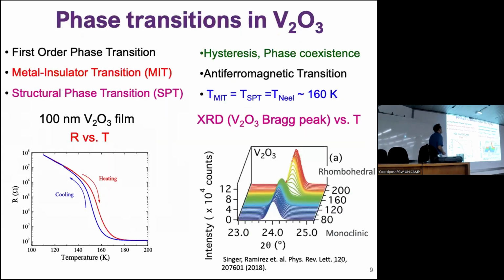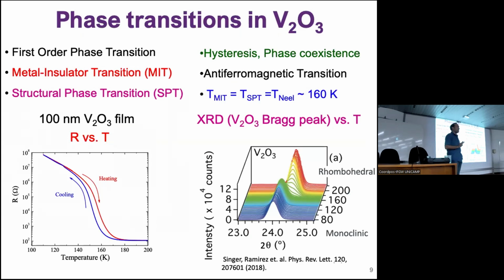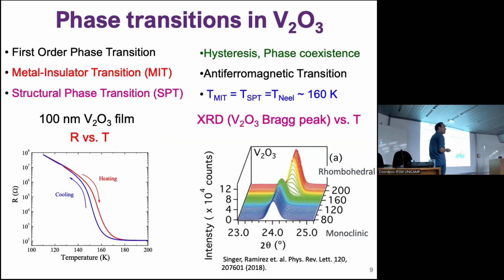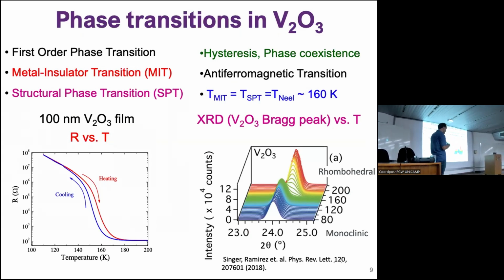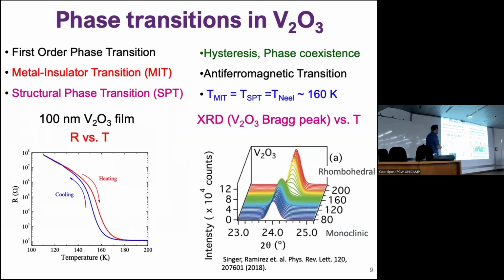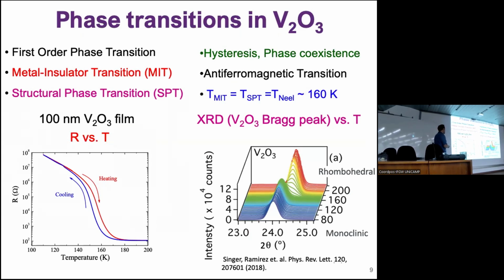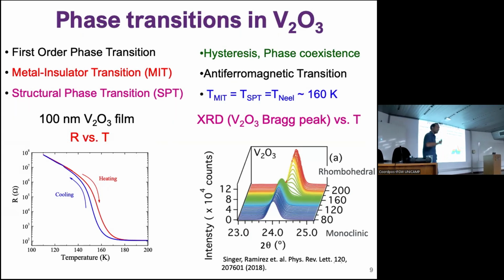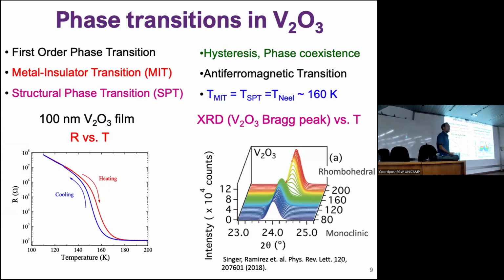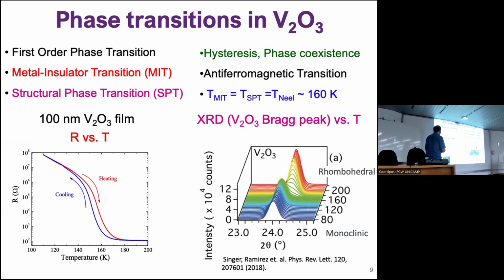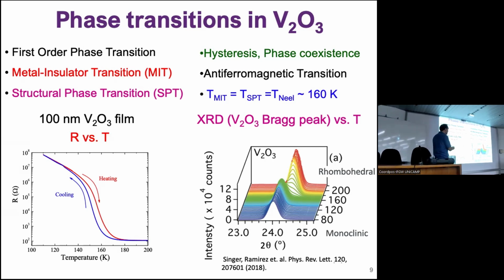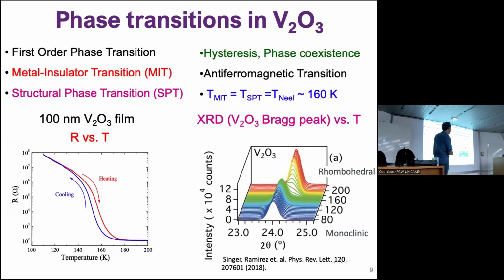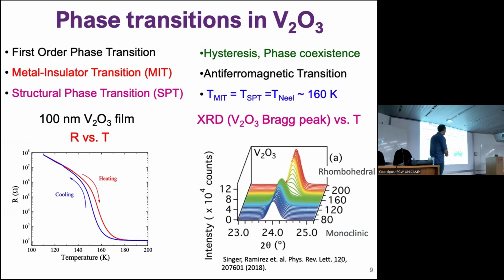Okay. There is another vanadium oxide I'm going to talk about today, and this is from the same family. This is V₂O₃, so this is another vanadium oxide. This one also has a metal insulator transition. It has the transition at low temperature in this case. The difference being that at low temperature it is an antiferromagnetic material. So it orders as an antiferromagnet. At high temperature, it's just a paramagnetic metal. And then there is also this hysteresis coming from the structural phase transition that occurs. At high temperature, the symmetry is rhombohedral, and then the structure is more monoclinic at low temperature.